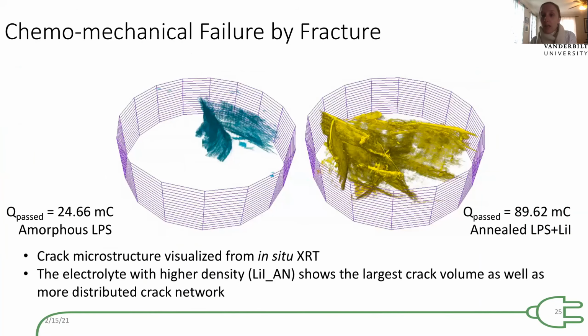With X-ray tomography, we cycled samples and tracked how the fracture event happened, both at the interface and within the bulk. These are characteristic examples of what the failure looks like in the amorphous samples, where we've only cycled a small amount of charge. And then our most robust sample, which is our annealed and attrition milled sample with the highest density part. You can see there's a drastically different fracture pattern depending on the mechanical properties of the solid electrolytes.